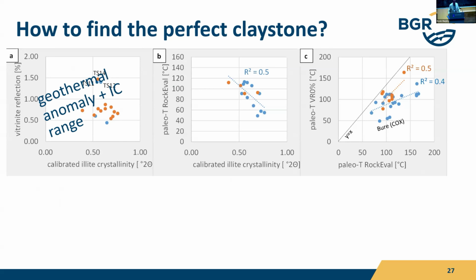And as well, we have a geothermal anomaly for the Hils-Mulde samples. There's an intrusion next to the clay formation, and the material really experienced much higher temperatures. So that means that the vitrinite reflection is high, although the crystallization of illite did not really occur, right?